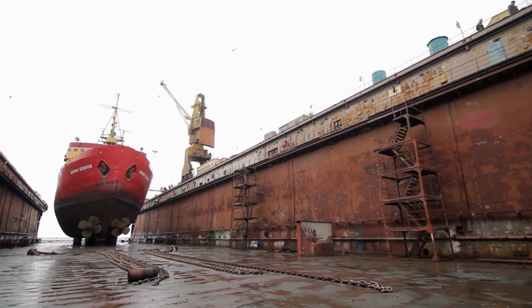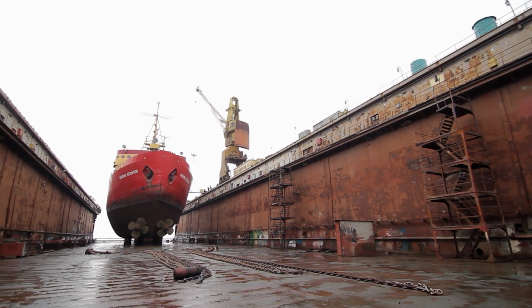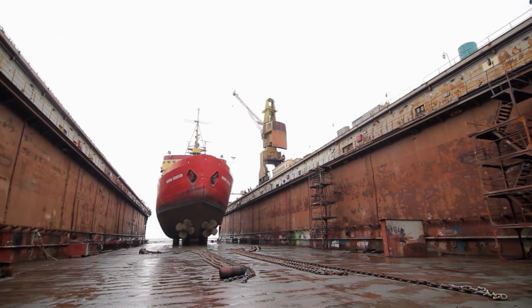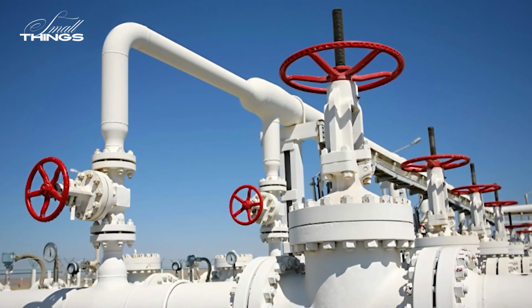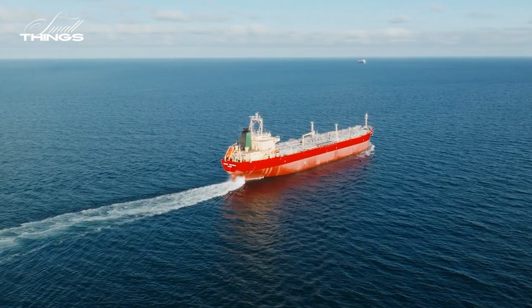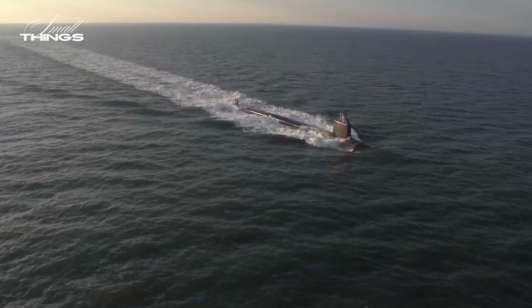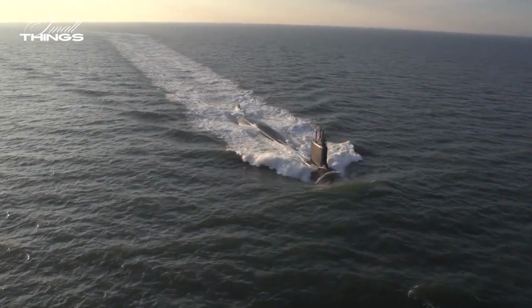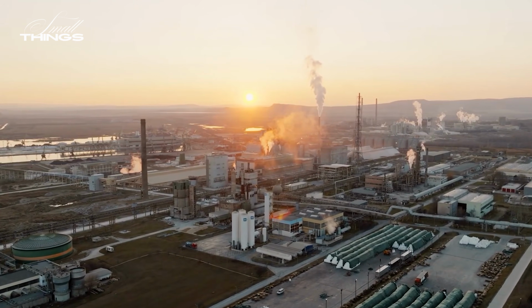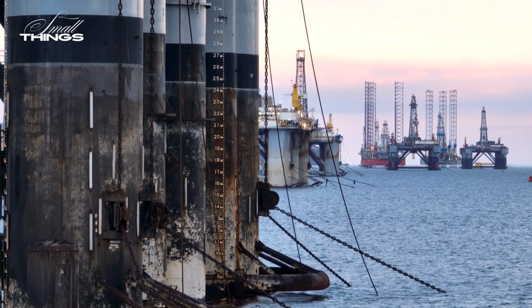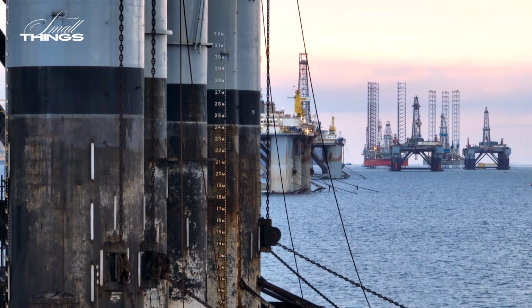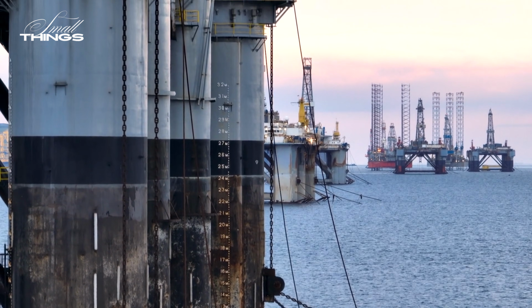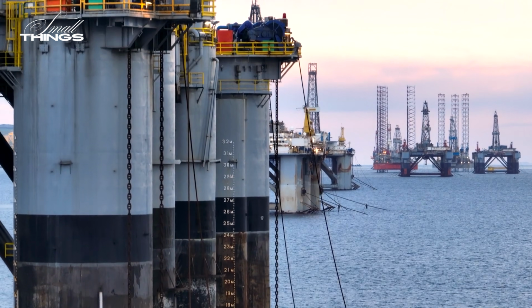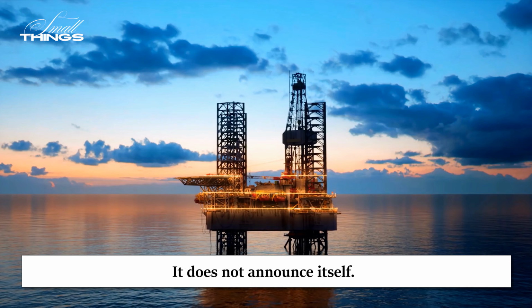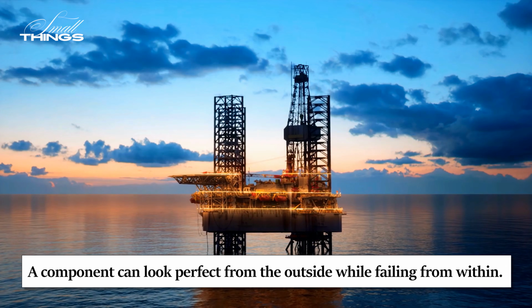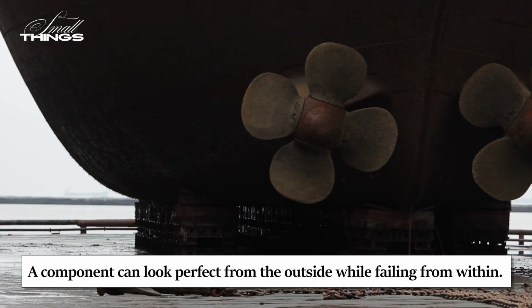In seawater, the chloride ions that make salt corrosive do something specific to stainless steel that they do not do to Monel. Stainless steel protects itself through a thin passive oxide layer on its surface. In most environments, that layer is stable and effective. But in high chloride conditions, particularly under mechanical stress, chloride ions penetrate and break down that layer. The metal beneath corrodes. The process is invisible until the structure develops a crack. Engineers call it stress corrosion cracking. It does not announce itself. A component can look perfect from the outside while failing from within.